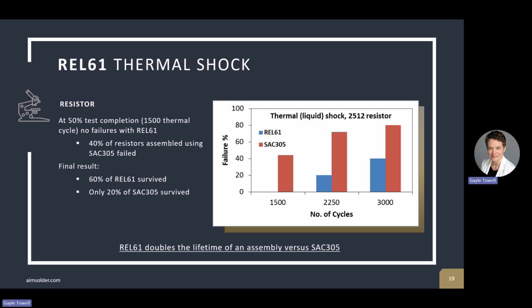This is a thermal shock test, so we change the temperatures more rapidly and see how these alloys perform. At 50% test completion, there were no failures with REL61, whereas 40% of the resistors assembled with SAC305 had failed by this point. In the final result, 60% of REL61 joints survived, while only 20% of SAC305 joints did. REL61 essentially doubled the lifetime of an assembly compared to SAC305 under thermal shock conditions.